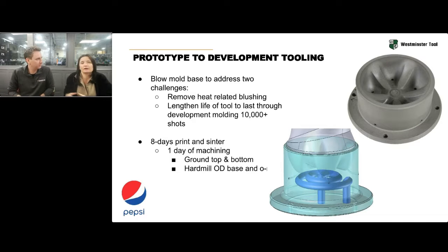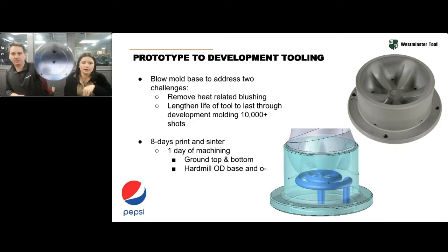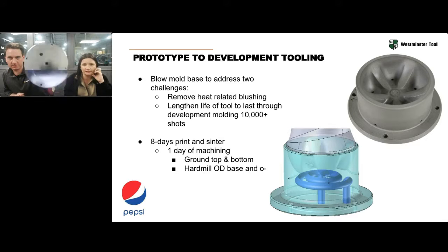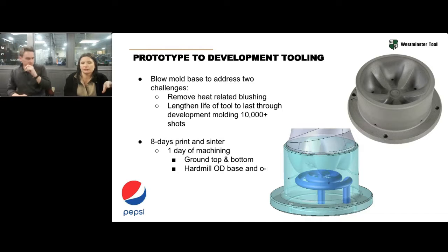In their existing format, they were using a plastic 3D printed base, and it held the heat a lot. So after a certain amount of shots, it started to get a lot of blushing and cloudiness, and that quality really impacted its ability to integrate with automation. So what we did is we printed them with Mantle. We did very minimal post machining. We ground the top and bottom just for shutoffs, and we hard milled the OD base. So very little machining afterwards.